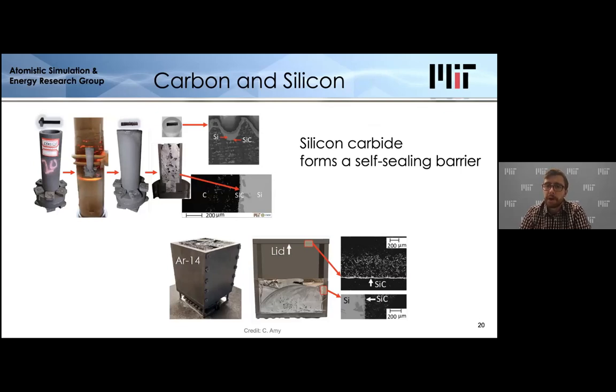So it turns out carbon and silicon form silicon carbide, which is a ceramic compound of the two when in contact with each other at high temperature. And it turns out that if you contain molten silicon in a graphite crucible, it actually forms a self-sealing barrier of silicon carbide where the silicon and graphite interact. So this silicon carbide layer forms, it thickens, and then it essentially prevents silicon from getting through, and it prevents carbon from getting out, and basically stops that reaction in its tracks. Now, this is a great solution because we're no longer worried about silicon and carbon reacting because they're not even touching each other. They have this intermediate layer that's able to shield them from each other and prevent these reaction problems that we've predicted.